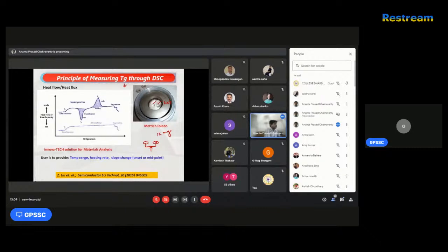When our sample requires heat energy to change its phase or change its behavior at different temperatures, then in the reference sample that heat will be released. If here it is absorbed, then in the reference it will be released. If in our sample the heat is released, then in the probe it is absorbed. With respect to this alternating phenomenon, the trend of endothermic and exothermic peaks comes, and from that the different thermal analyses like glass transition temperature at the fast change in slope, crystallization behavior, melting behavior, softening temperatures, and melting temperatures, can all be understood from this differential scanning calorimetry.